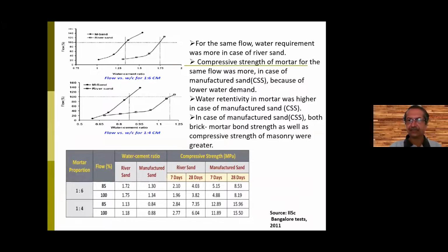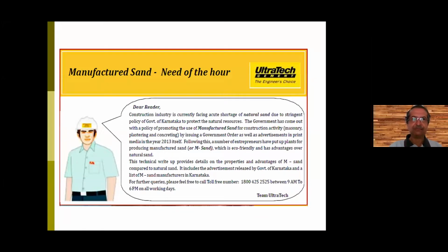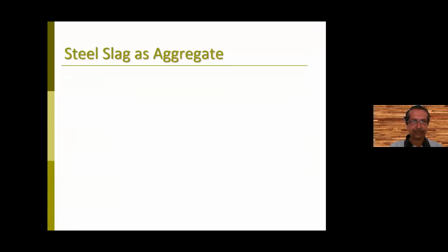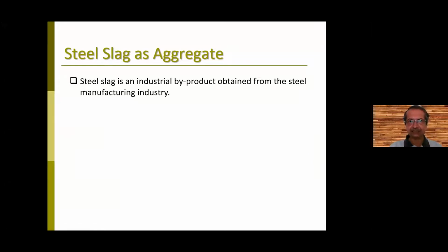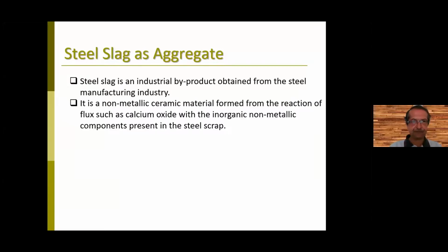In the case of manufactured sand or CSS, both brick mortar bond strength as well as compressive strength of mortar were greater. So quite some detail is available in the tech mailer, which is produced by UltraTech on manufactured sand. You can go through that for more details. There is also talk of steel slag as aggregate. Steel slag is an industrial byproduct obtained from the steel manufacturing industry, which is a non-metallic ceramic material formed from the reaction of flux like calcium oxide with the inorganic non-metallic components in the steel scrap.